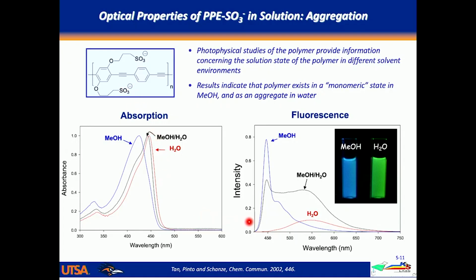By contrast, in water, the fluorescence is weird. It's green in color by eye, and if you measure the spectrum, it's this broad sort of emission that peaks at about 550 in the green region of the spectrum. And at first we were confused. I told Chunyan, go back, try again. There's something wrong with your solvent. I don't understand what's going on. It turns out this is very repeatable. There is clearly some effect that's taking place.